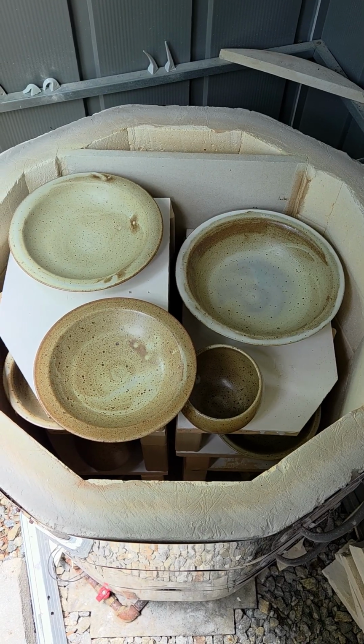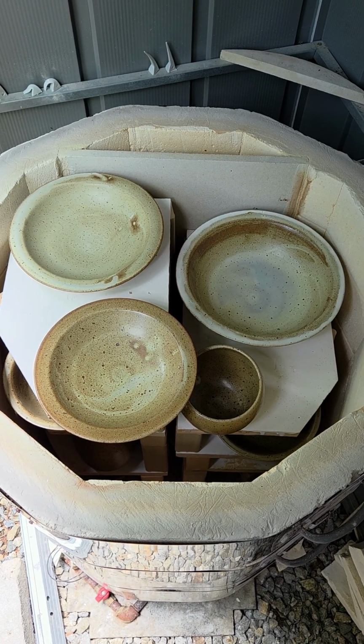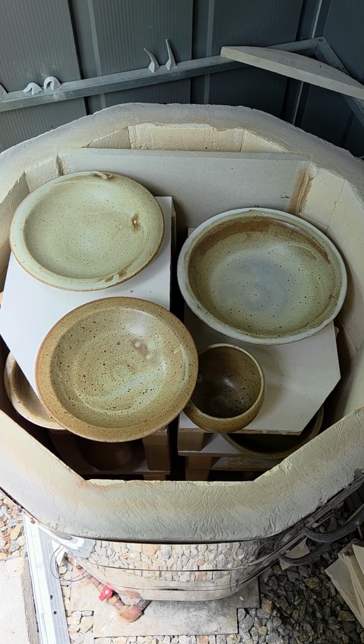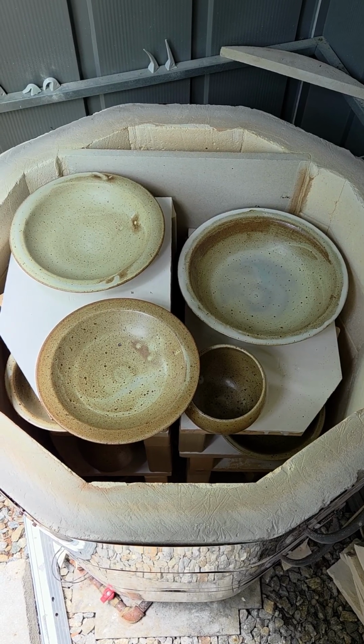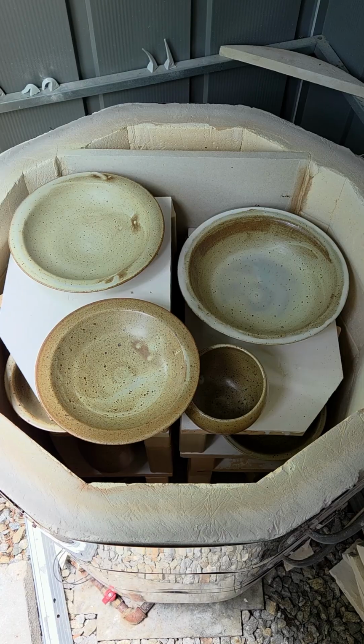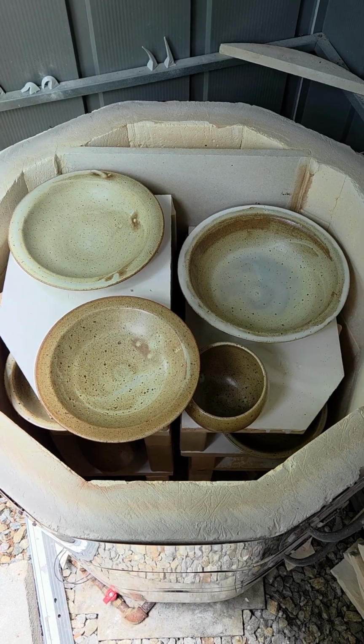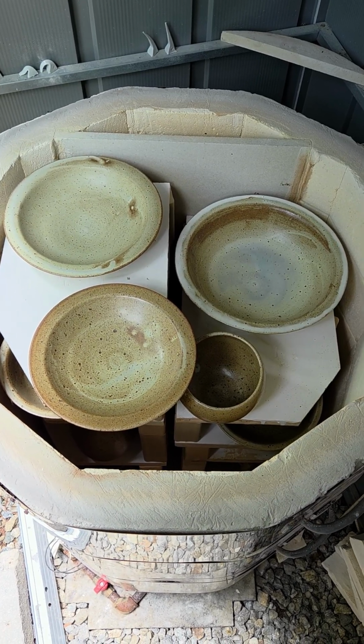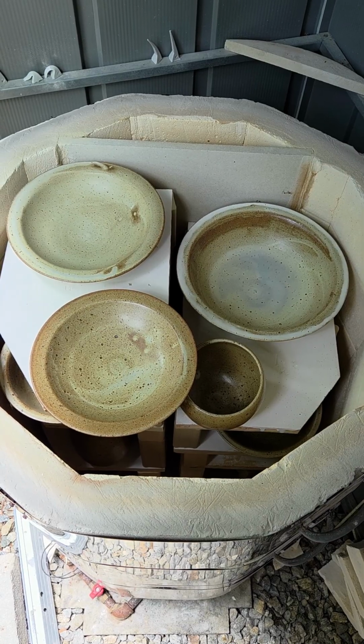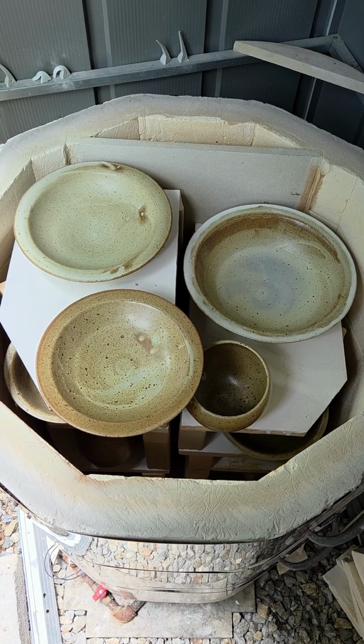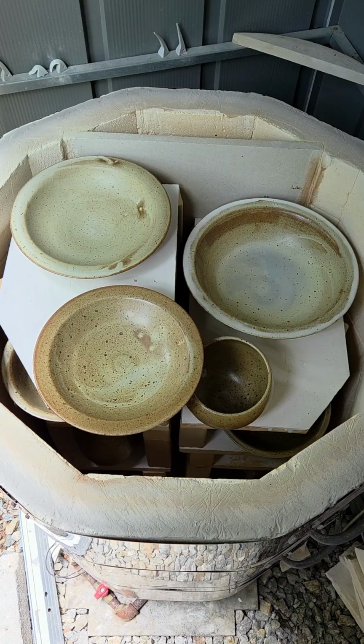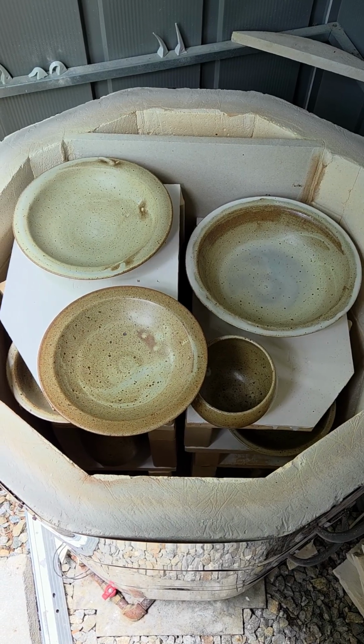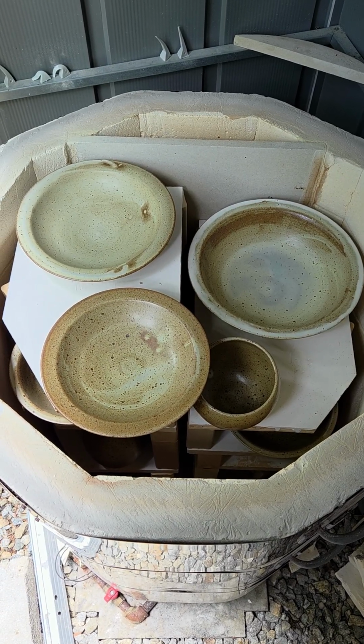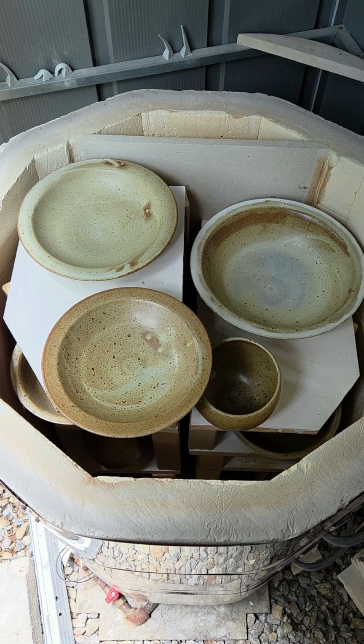This is the kiln opening the next day. It had cooled down to about 100 degrees centigrade, and so I've opened up the lid, and just let things continue to cool down. Reduction was strong, probably a little stronger than I anticipated, and that's what I kind of realized towards the end of the firing, as I mentioned during the video.